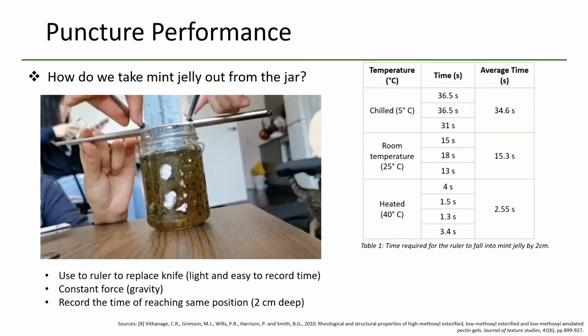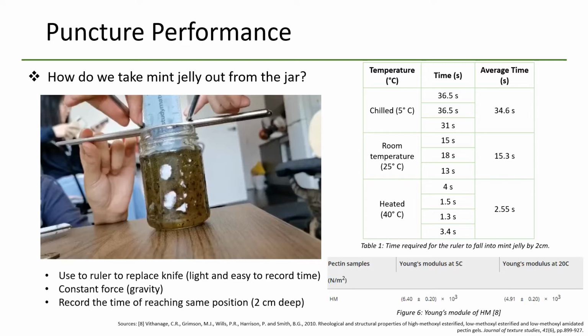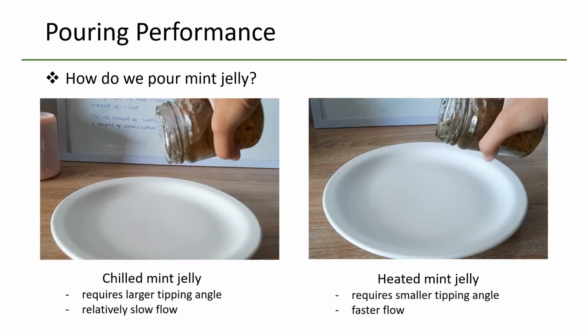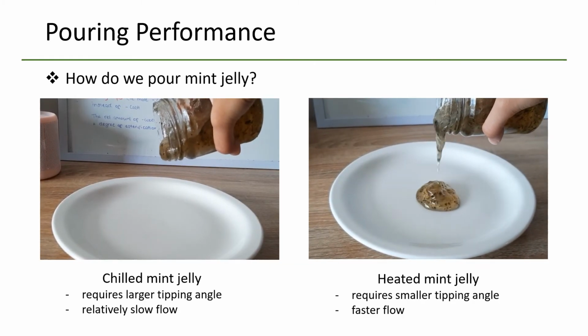From the puncture test research, it mentions that the high methoxyl pectin has the largest gel strength compared to low methoxyl and low methoxyl amidated pectin. Furthermore, the high methoxyl pectin has a larger Young's modulus at 5 degrees than 20 degrees because the increasing temperature will destroy the hydrogen bonding of high methoxyl pectin with water. This can also explain our experimental phenomena, and the recommendation is choosing your favorite texture and then deciding how to cook it. Consumers could also use the mint jelly by pouring it directly out of the jar.